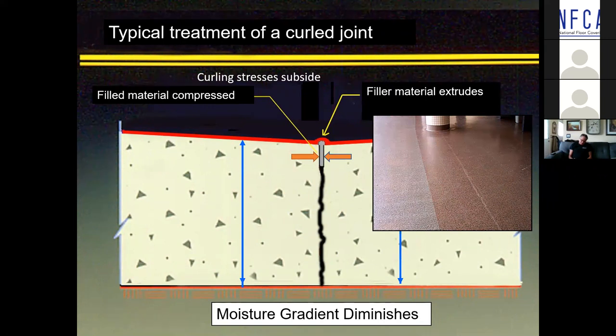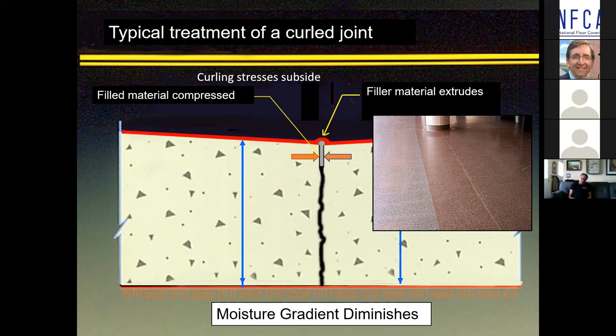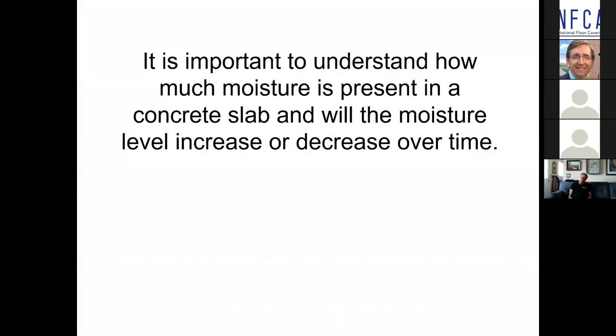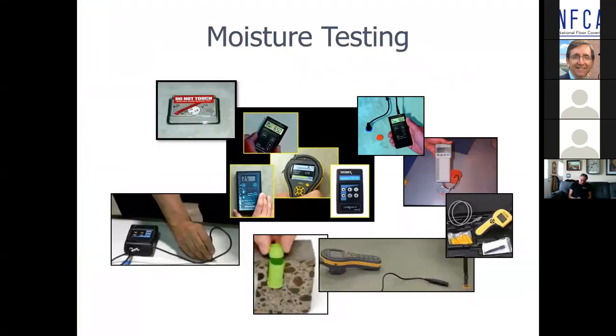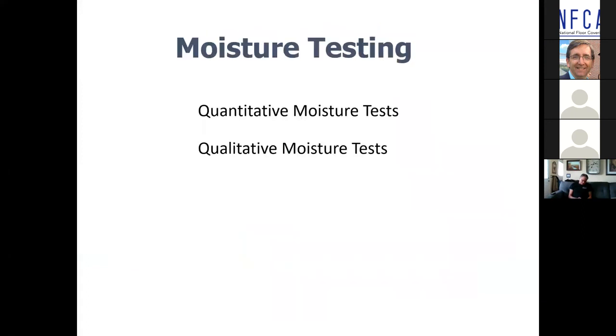But please be aware, if you're going to put a flooring system down and you run that level across those joints, teeter-tottering, just grinding it level, or leveling it with an underlayment material isn't necessarily going to solve the problem. So it is absolutely critical to know how much moisture is in that slab and whether or not the level of moisture in the slab is going to increase or decrease over time, which leads us to how do we make that determination? Well, moisture testing.